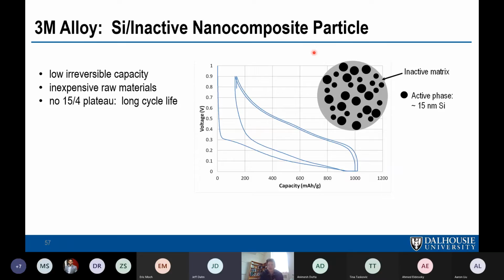And again, this is an inverted slide. You can see I put this slide together in the inverse way, which is incorrect. If the 3M alloy did look like this, then the lithium would never be able to reach the silicon phase because the alloy is completely inactive towards lithium. So this is an inverted drawing, not a good drawing.